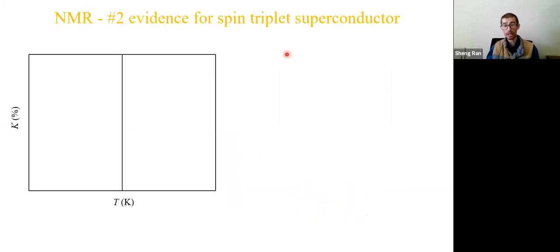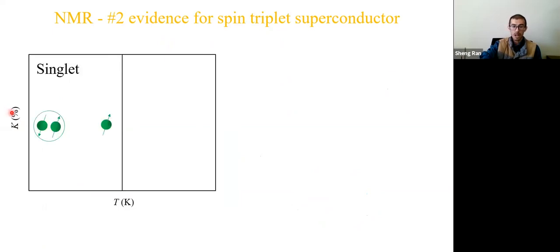So is there any evidence? One way to probe the spin susceptibility is the so-called NMR measurement. The NMR Knight shift directly measures the spin susceptibility. If this is a spin singlet pair, at high temperature we have spin half electrons. At lower temperature, two spins, spin up and spin down, give you total spin 0. Spin susceptibility is supposed to decrease and eventually go to 0.